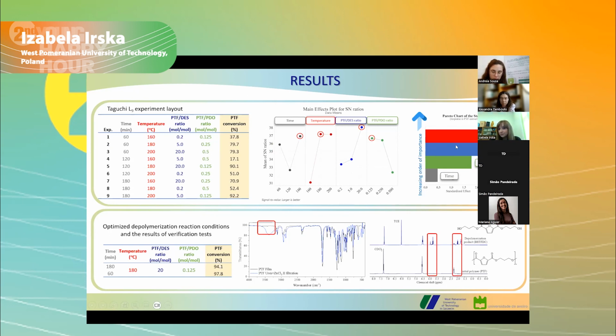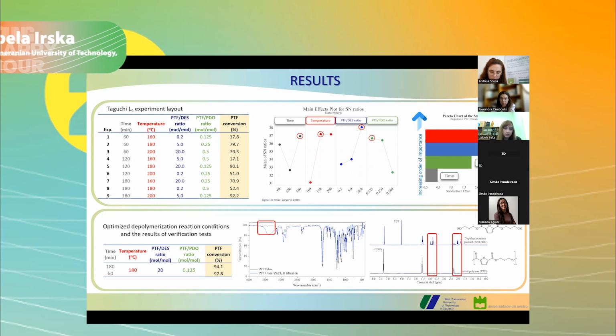Knowing that the time does not significantly affect the results, we were curious and decided to carry out the test again using the lowest value of this parameter, so just 1 hour. And again, we were able to obtain excellent results, and the conversion in this case was around 98%.